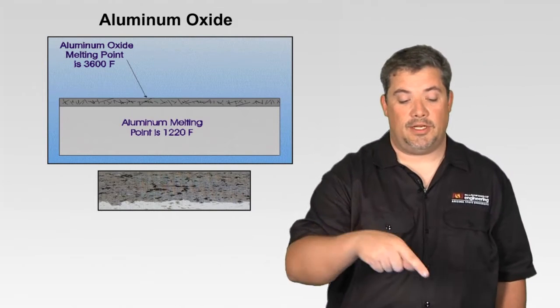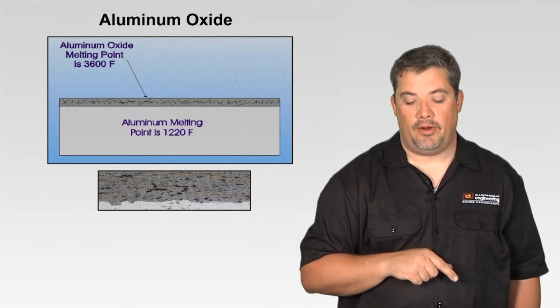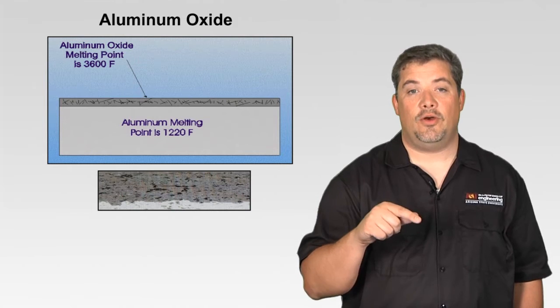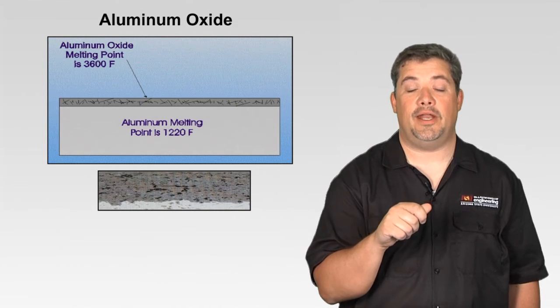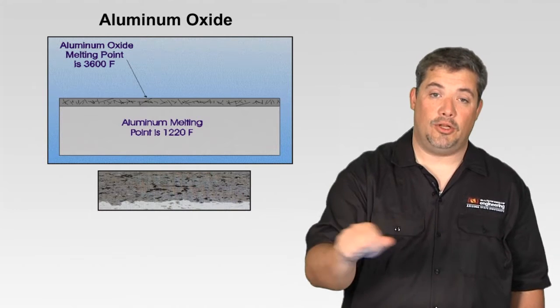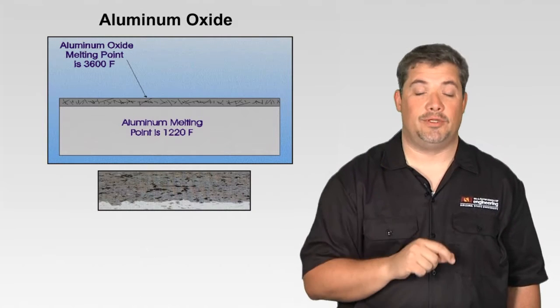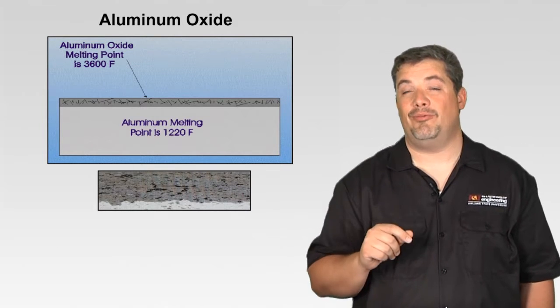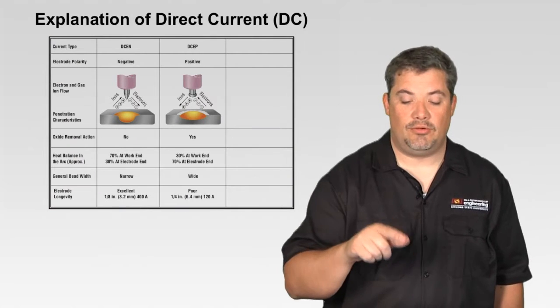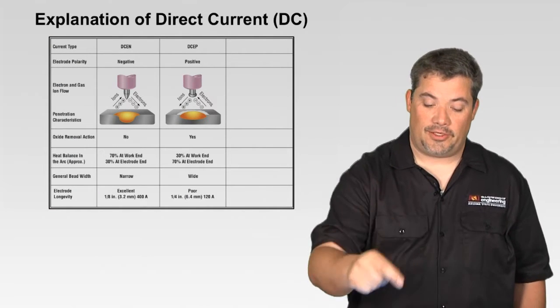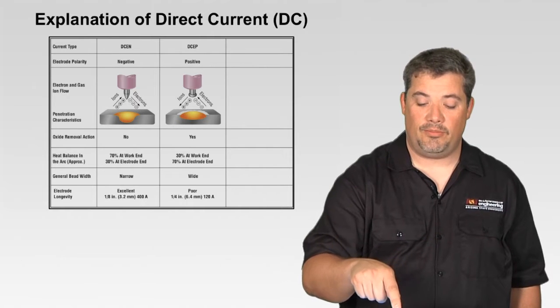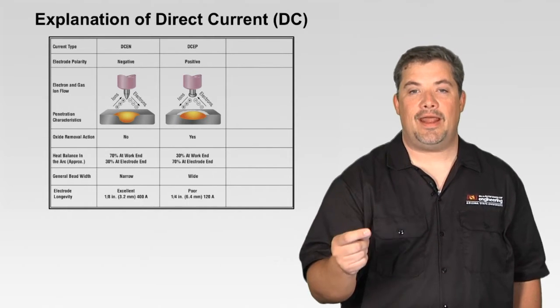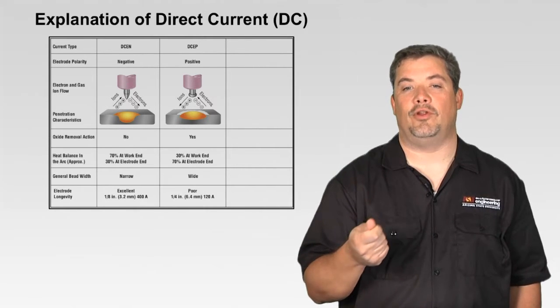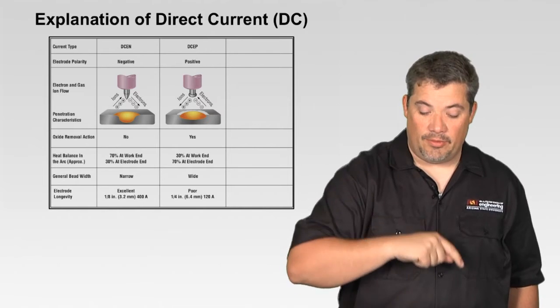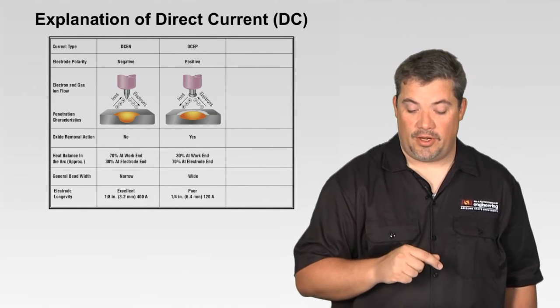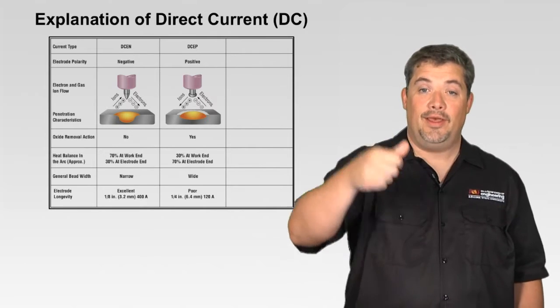So aluminum oxide melts at about 3,600 degrees Fahrenheit, and the aluminum underneath melts at about 1,220 degrees Fahrenheit. So we can never truly remove that aluminum oxide unless I was in outer space or in an argon bubble. I could maybe wire brush and move it away, but aluminum oxide forms almost instantly, and you can never get rid of it. You can only really thin it out. So that's where we use direct current electrode positive. Electrons and ions are flowing in the opposite direction. You can see there's a little bit of an etching zone or white around the edges. That electrode positive actually removes the oxide off of aluminum, for example, and its heat relationship is the 70-30, but in this case, 70% of the heat is on the tungsten and only 30% is on the part.